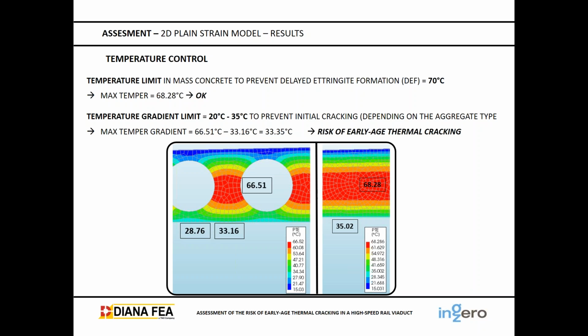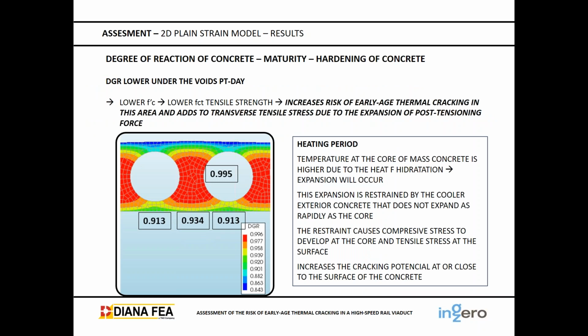Okay, we see here the images in which we can see the maximum temperatures and the gradient. Also, regarding the degree of reaction of concrete, or the hardening or maturity of concrete, the degree of reaction under the voids is lower than in the inner part, so it has lower compressive strength and lower tensile strength, so that increases the risk of early age thermal cracking under the voids. And also, if we add the transverse tensile stress expected due to the expansion from the post-tensioning force, it increases that effect. Okay.